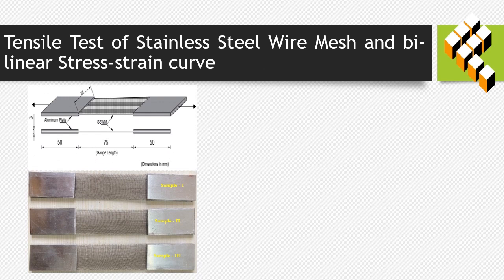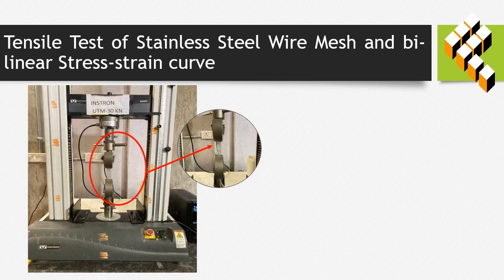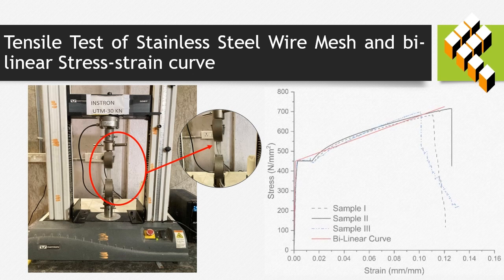The mechanical properties of SSWM, such as the modulus of elasticity and the tensile strength, are obtained through the coupon test. For simplicity, the stress-strain curve of SSWM is characterized by two straight lines. This bilinear curve is used for developing an analytical model for SSWM wrapped concrete cylinders.